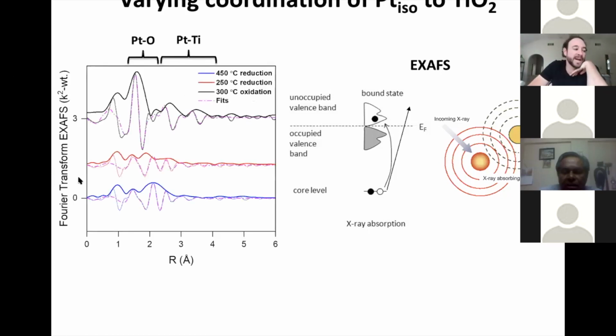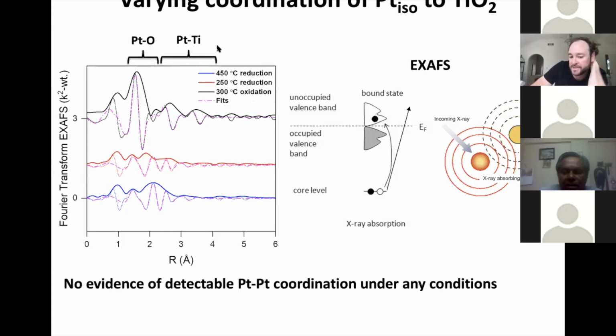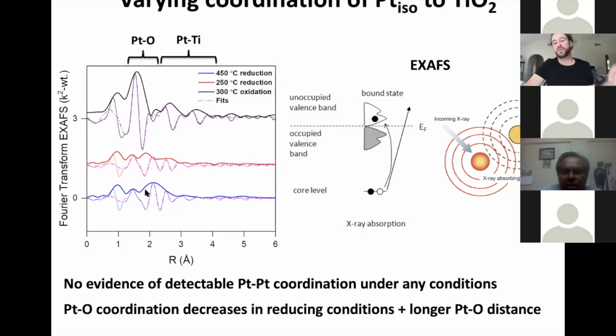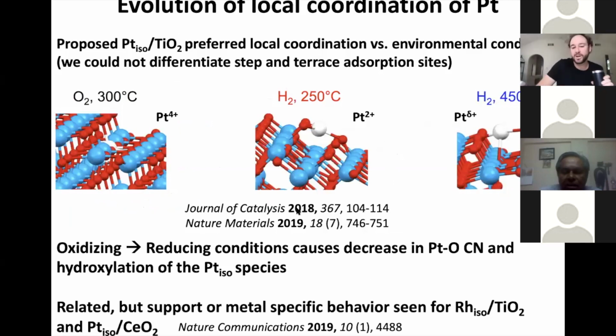So here what we did is we took EXAFS spectrum, and these are complicated wiggles, and I don't expect you to understand the details if you haven't looked at EXAFS a lot, for our platinum species under the 3 different environments we had looked at. You can decompose these spectra into the range where you have platinum oxygen coordinations and platinum titanium coordinations. And I'll say here that we had no evidence of direct detectable platinum-platinum coordination. So still is convincing we have these atomically dispersed species. What you can see is as you go from oxidizing to more reducing environment, the amount of platinum oxygen coordination decreases, and the interactions between platinum and titania change as well. So we put this whole story together, and I won't go through every detail, but it's all in these couple of papers here.